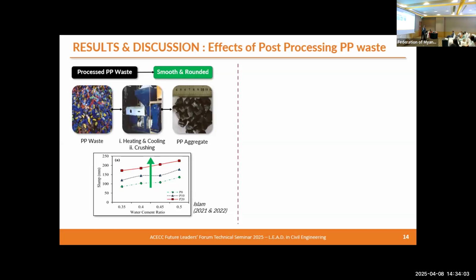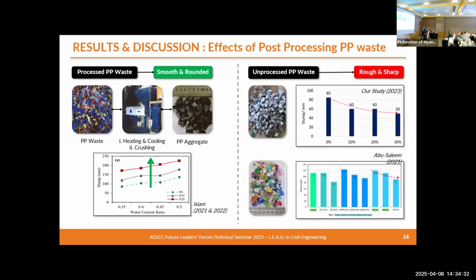We have concluded that when the plastic waste is post-processed, with post-processing including heating and cooling, then crushing into the same nominal size as the natural coarse aggregate it replaces. For example, if the nominal size of the natural coarse aggregate is 20 millimeters, we get the plastic waste, heat it, and crush it into the same size as the natural coarse aggregate. But in our case and some other researchers' cases, we directly incorporated plastic waste as it is, without any post-processing. That's why it's giving a negative impact.